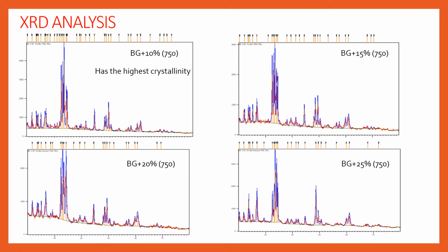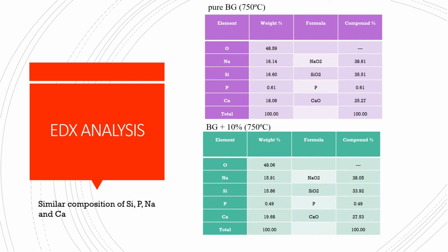For the XRD analysis, it was found that bioactive glass with 10% added CNF had the highest crystallinity. For the EDX analysis, it was observed that pure bioglass and bioglass with added CNF had the same composition, which proves that the addition of CNF does not affect the composition of the bioactive glass.